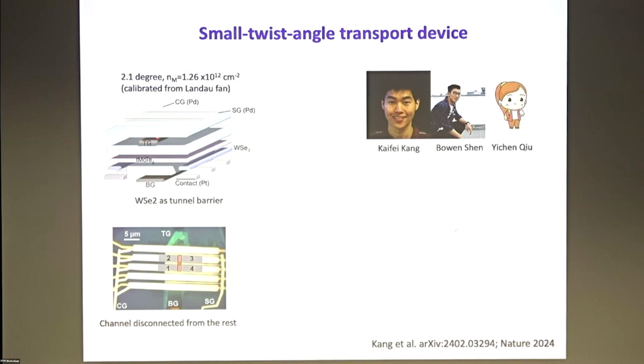It's a dual gated device. So this is the top gate and the bottom gate. And this is a twisted bilayer sample. And we use platinum contacts to try to reduce the contact resistance. I will talk about that. And in addition to that, to improve the contact, we use a monolayer of tungsten selenide as a tunnel barrier that separates the sample and the contact.